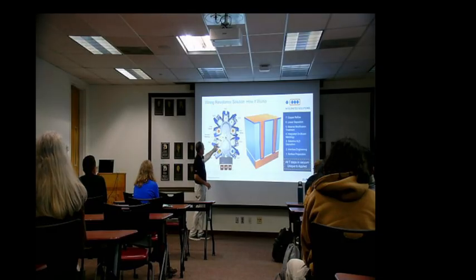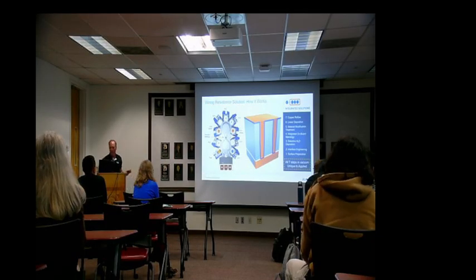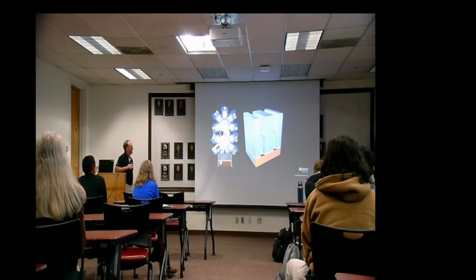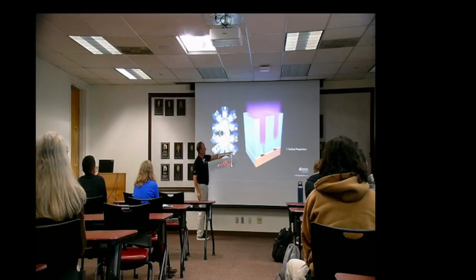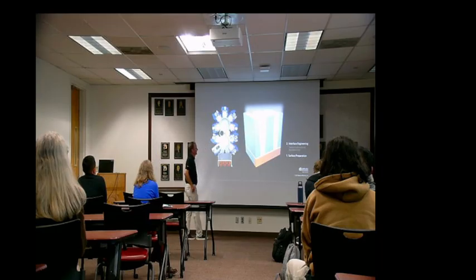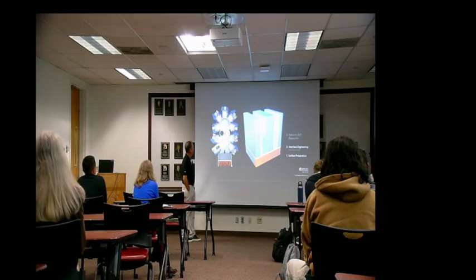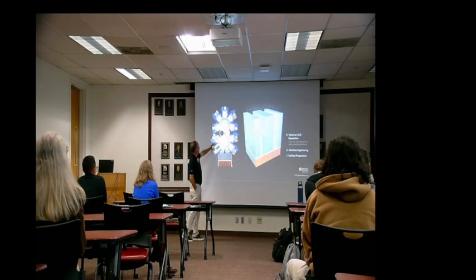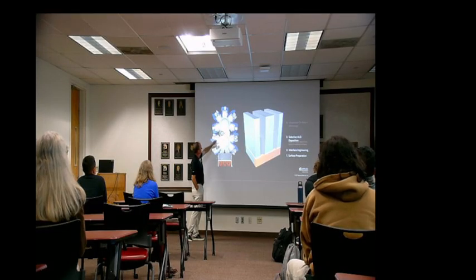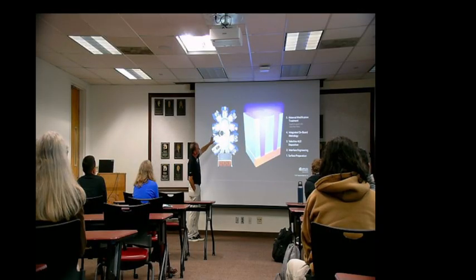another series there. I won't go through too much detail, but you'll see the wafer going through all these different chambers in order to put down the metals that we want. And while the wafer is going through these different chambers, it's going to tell you what's being done. That's the cleaning, surface prep, and you'll start to see what it's doing inside the features. So that's an ALD process, atomic layers being put down on the side of the feature. This is metrology. We're measuring the thickness to make sure we've got that right.